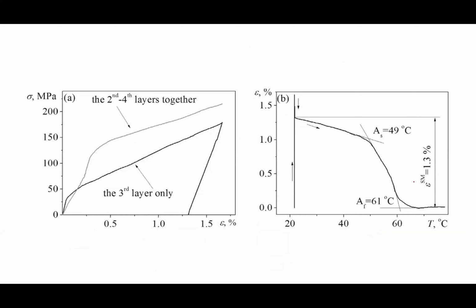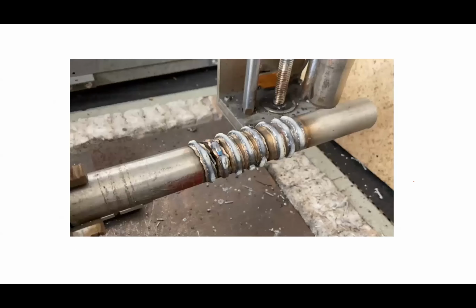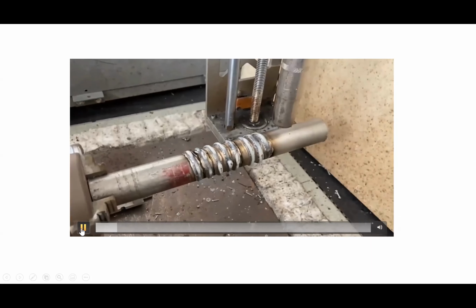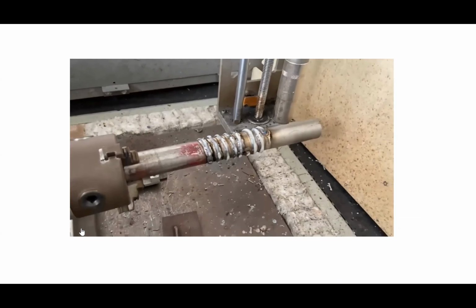Okay, with this as an idea, we did a stress strain analysis to study the pseudoelastic behavior, as well as the austenite start and austenite finish of the surface. We could observe that the pseudoelasticity property was behaving in a very good way, whereas with respect to the shape memory alloy property, we could have better actuation characteristics coming out of it. In fact, this is a video in which we were involved in fabricating a spring-like structure. This is a wire arc based additive manufacturing head.